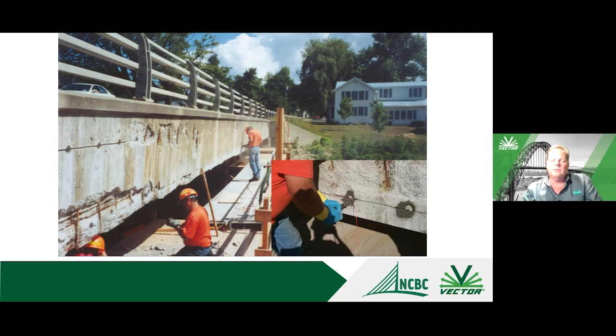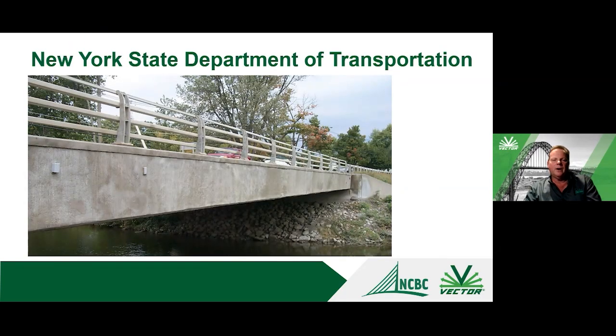This is a project we were involved in, quite a while ago, in upstate New York, where they had adjacent box beams, and really the corrosion problem here was just on one side where you had the drainage from the deck contaminating just the outer face of the one beam. And eventually this beam was going to be replaced, but to hold it in place, they wanted to not only do the repairs, but use the type 2 anodes to provide localized protection to the area that's actively corroding, just to hold it in place until they could replace the one beam on the structure. So this is an example of what you might want to call targeted protection. You're just using anodes where you have a known risk of corrosion and targeting them in that fashion. There's the completed repairs.